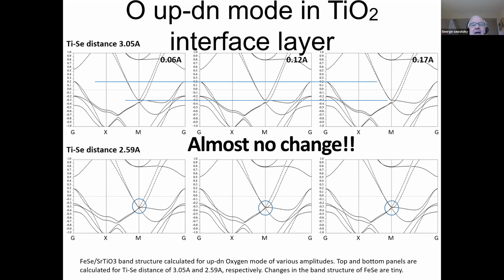Okay, so we then did 2 things. These are DFT calculations. We just moved the oxygens up and down relative to the titanium. Another way is to stagger them, the up-down mode. I show here the up-down mode because that's the one that is expected to couple most. That, of course, is the transverse optical phonon, and because it's at the zone boundary, it has a large Q.